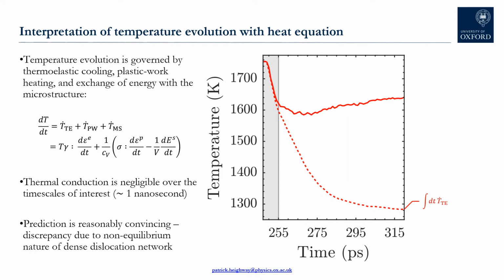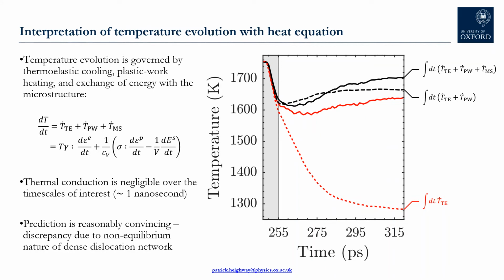The graph on the right shows once again the measured temperature evolution during shock release in the solid red curve, and also the release isentrope, which is obtained by integrating up the thermoelastic cooling term only. We can now overlay the solution to the heat equation obtained when one switches on plastic work heating, and you can see that plastic work heating alone can account pretty convincingly for the unexpectedly high release temperature. However, it's clear that the shape of the release path leaves something to be desired. It departs way too quickly from the isentrope and is a bit too flat at late times. However, if we also switch on the defect term, the agreement becomes much better. The reason the temperature drifts up slowly at late times is thermal energy being recovered from the gradually diminishing dislocation network that's created by the shock.